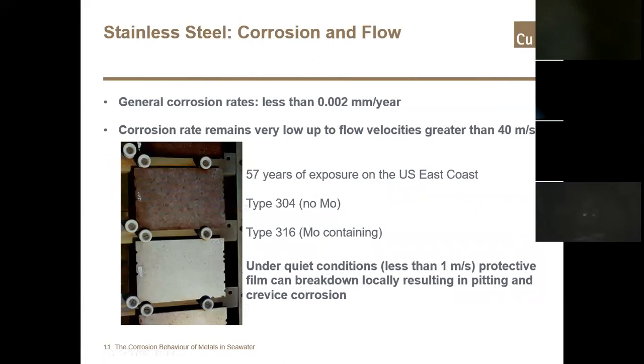Stainless steels generally rely on the movement of seawater across the surface to prevent deposits and marine growth from forming, and it discourages local pitting. If the water is flowing, generally a velocity of around 1 meter per second is needed to prevent any pitting corrosion in seawater. The general corrosion rate of stainless steel is very low.